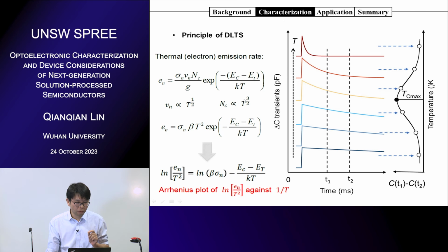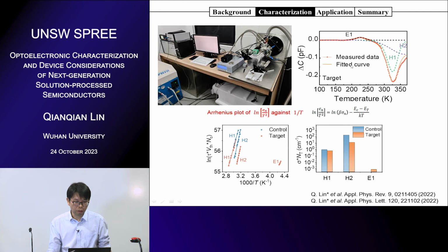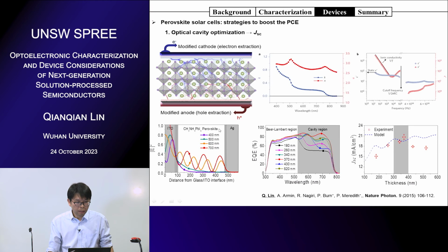So this equation we talked about, we can modify to here. This signal we get from the DLTS measurement, and it depends on the temperature. If you can fit the value of this one, we can get more information about the energy level of these trap states. This is a typical setup in my group. We use DLTS to measure the deep states. And that's all for the characterization of semiconductors for both mobility and trap states.